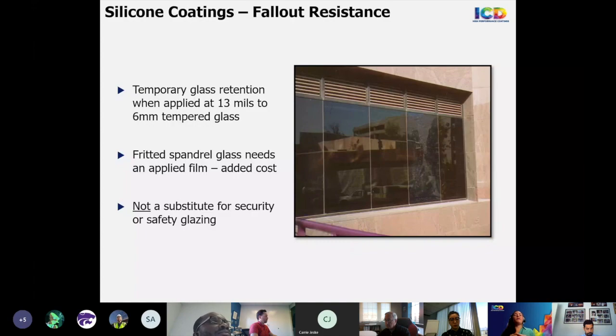And I just wanted to point out a unique characteristic of silicone, which has an elastomeric nature. So it gives it the ability to naturally achieve fallout resistance when applied at a certain thickness. So fallout resistance refers to 6 millimeter tempered glass that, if shattered, can be temporarily retained into the building until it can be replaced by the owner. And if you apply silicone at 13 mils wet film thickness, it automatically qualifies for that fallout protection, while ceramic Frit needs an applied film, which can add cost, added material, added labor. So this is a cost-saving strategy.